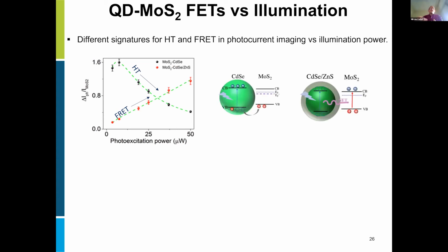One explanation that we came up with is, remember, photoexcitation of the quantum dot next to the MoS2 material moves just a hole into the two-dimensional material, so we are left with negative charges here. So the more photons we absorb, the more negative charges we create. This will act as a photo gate on the two-dimensional material, inhibiting creation of external current. And that's why we see this behavior here when we put in more photons. So the photo gate is going to suppress the creation of the current.